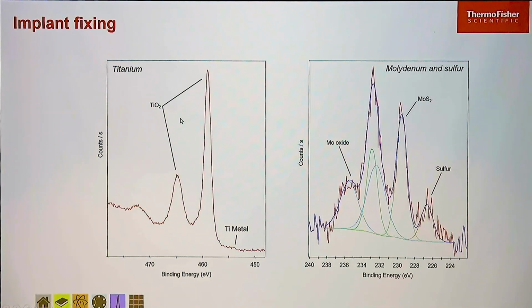So firstly, looking at the region around the head of the screw. So titanium metal, we can see a little bit of the metallic signal. It's mostly quite oxidized. And then in the molybdenum region, we can see also sulfur, peaks for molybdenum disulfide, and some of that presumably is a little bit oxidized, so we can see molybdenum oxide as well. Now, molybdenum disulfide is quite often used as a lubricant. In various cases, we use it on the UHV systems because we can actually put it in vacuum and it doesn't cause us any problems. And so this looks like it's not quite been cleaned off the part after machining.